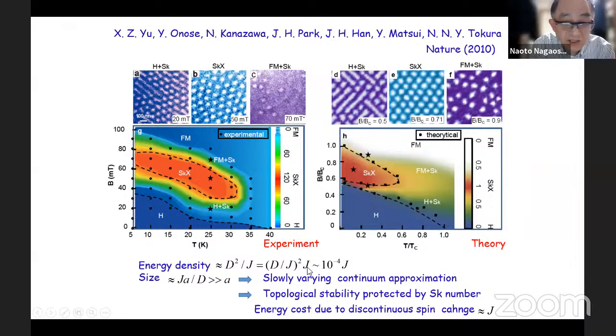The one is given by J. J is a ferromagnetic exchange coupling, which determines the TC of the order of 30 or 40 Kelvin. But there is also the Dzyaloshinskii-Moriya interaction D. And then D squared over J is a typical energy gain due to the twist of a spin. And this energy scale is much smaller than J. So this corresponds to a very large length scale of spin texture, namely J over D is bigger than unity. So this means we can apply the slowly varying continuum approximation.